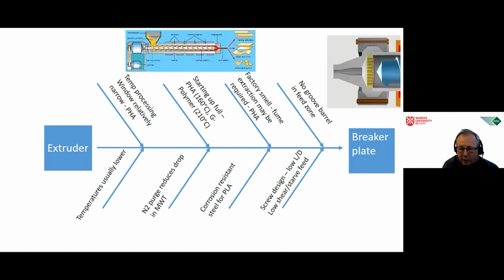where the processing temperature and the screw speed can affect it. It's fairly sensitive to both temperature and screw speed. And this is because the melt viscosity can change substantially across even a 10 degrees C temperature range, which can change the extrudate from a running liquid if the temperature is too high, or cause high torque from a viscous material if the temperature is too low.